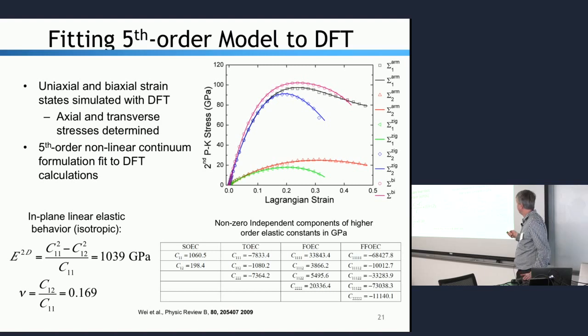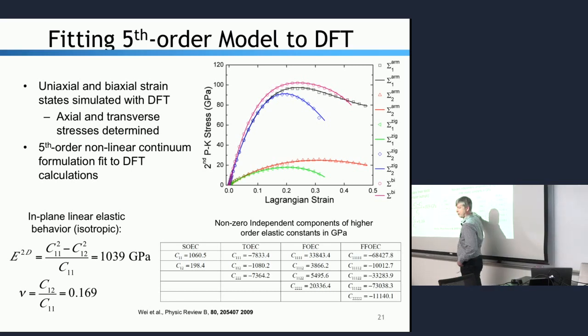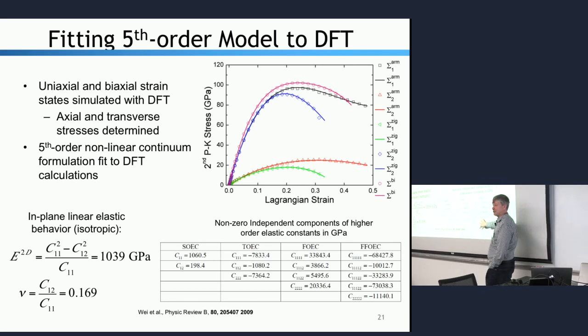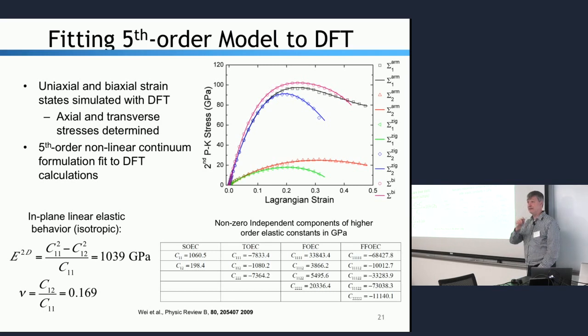And the important thing we learned here is that if we ignored even this highest order term, if we only took, our original theory was here, if we took just one extra set of terms, it still wasn't enough to fully reproduce these curves. We had to go out to this fifth order in energy. Yeah. Everything is in plane. Everything is in plane. Yeah.